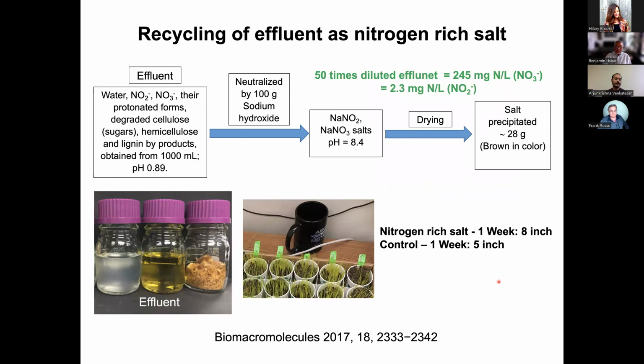And the beauty about our process is that it's really a zero waste process, because after the treatment, we separate the solid part, which is nanocellulose, and the liquid part, which is the effluent. The effluent still consists of nitrite, nitrate, and also degraded cellulose, degraded hemicellulose, and lignin. So we can neutralize them back to this salt. And the salt is very similar to inorganic fertilizer salt, except that it also consists of 30% organic compounds. So it actually gives you a slow release fertilizer process.